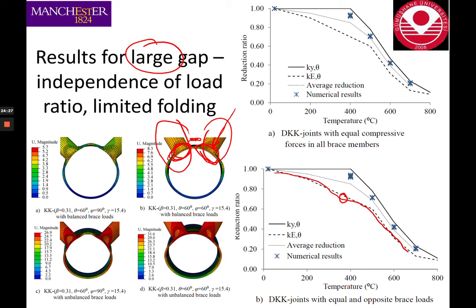Therefore, we found that approximately the strength reductions at high temperatures are higher than that. In fact, they're a bit closer to the average of these two values, yield stress and Young's modulus. And that is when we have equal compressive forces in both brace members, or when we have opposite brace forces, because this could happen. So what we recommend for large gaps is to use the average of these two values to modify